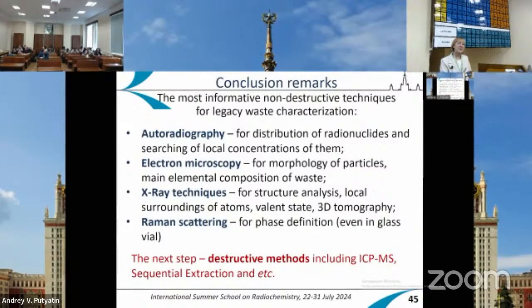And micro-Raman scattering could help us in some cases for phase definition if you have a library of reference materials for it, because it is fingerprint analysis. And after that, we use destructive methods, including ICP-MS and sequential extraction, to see the partitioning of radionuclides among different fractions of mobility, and so on.